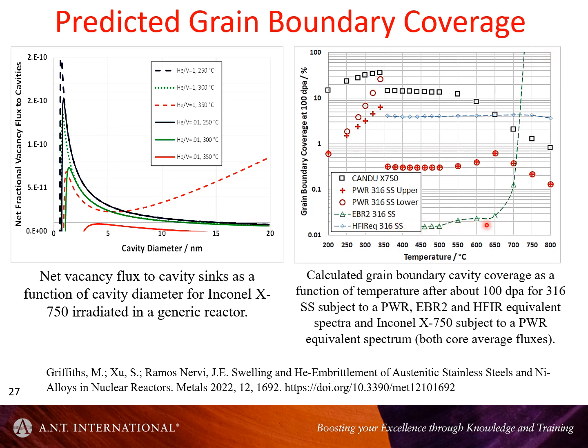Note also, in terms of coverage, if we had an EBR2 situation where there's very little helium, but there will always be some helium even in a fast reactor. But because of that, the balance tilts in favor of getting more coverage on the boundaries. So in EBR2, the coverage rapidly increases as we increase the temperature. That's in part because of having too little helium in the material. So you don't get a lot of swelling. The internal microstructure, basically the swelling drops off at a high enough temperature, whether you calculate it or whether you measure it. But there's still enough helium to get to the boundaries and cause you some problems.